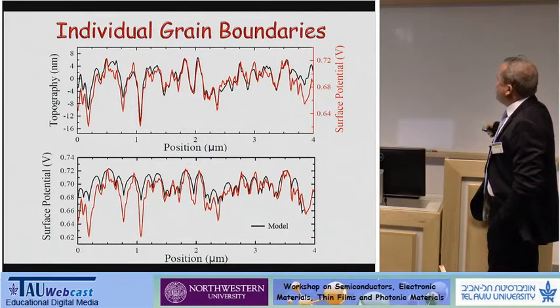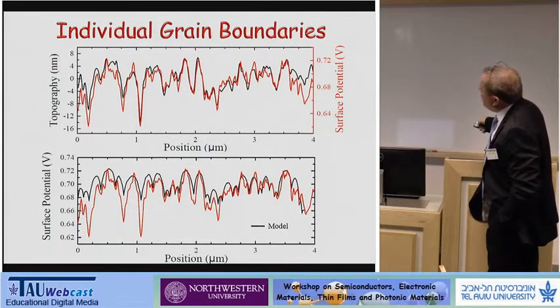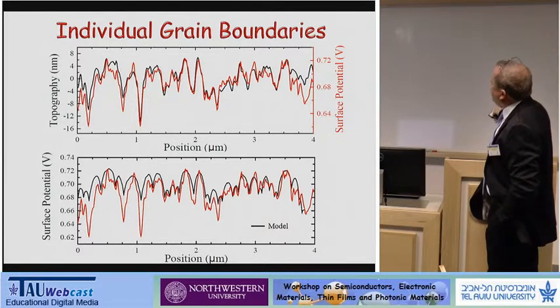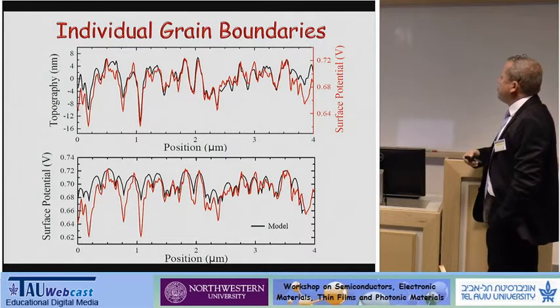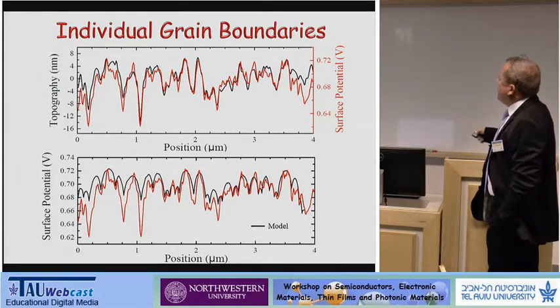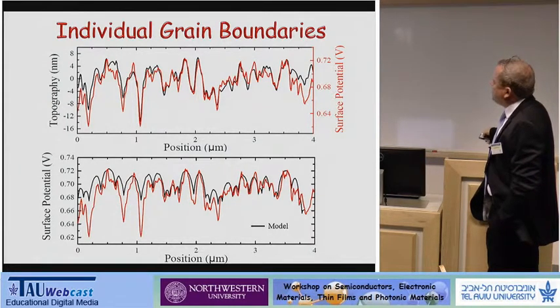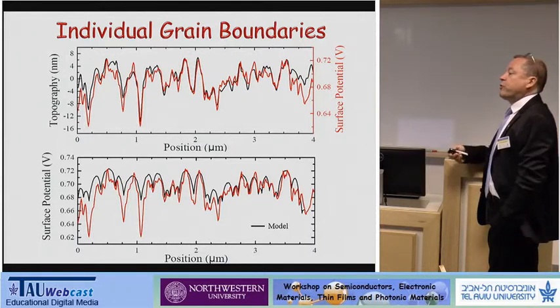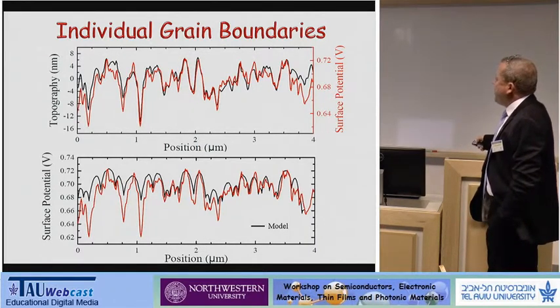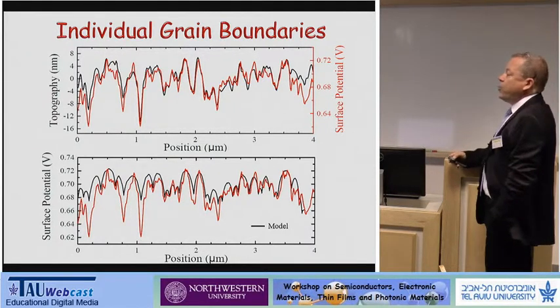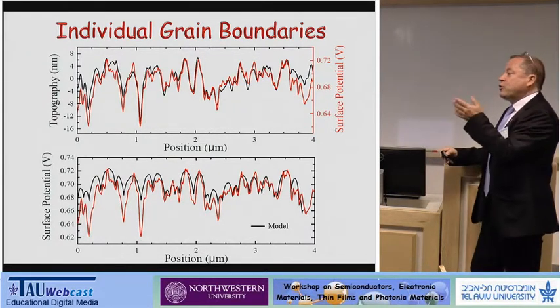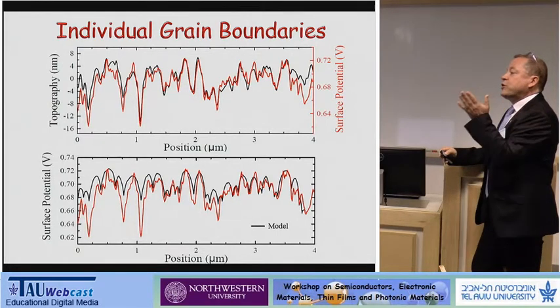So each time you see, I'll slow down a little bit, the black is topography, and the red is the surface potential. You might think that this is an artifact, but I'll prove to you in a second that it is not. And here you see a fit to the surface potential. The red is exactly this surface potential measurement, and the black is a fit, a solution of the Poisson equation to this problem. And by fitting this, and we think this is a fairly good fit, we can obtain the individual interface state concentration at the boundaries.